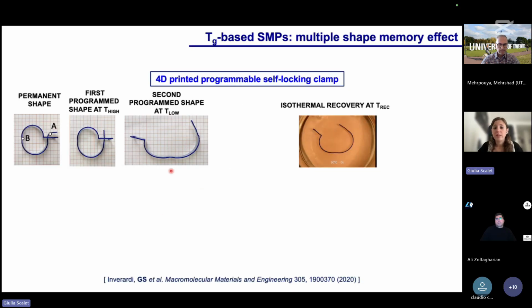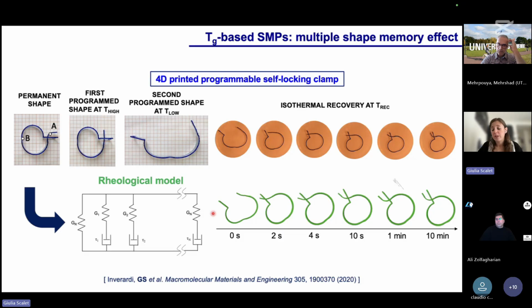And you can also play with this effect in order to achieve a more complex structure. This is a very simple example of a self-locking clamp. So essentially this is the printed one. This is the deformed shape during the first programming step. This is the second shape at the second programming step. And finally, we can recover sequentially this deformed shape up to the initial one in a sequential way. So this allows to close the clamp. And we support this experiment also with numerical simulation.